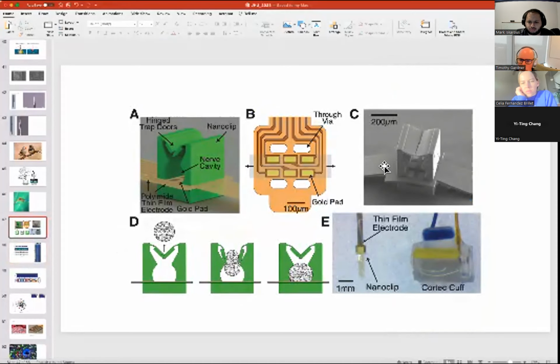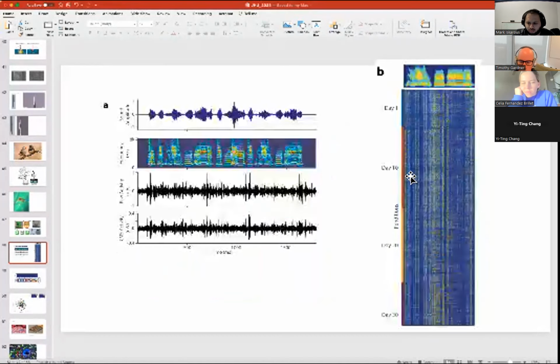We could do really effective common mode subtraction of those signals. So take the average of all 6 electrodes and subtract it from each individual electrode in order to erase movement artifact as much as possible in recording from these small nerves. And this is an image of songbird vocalization, just 3 syllables, and then the raster plot of activity recorded from the surface of that nerve across 30 days.